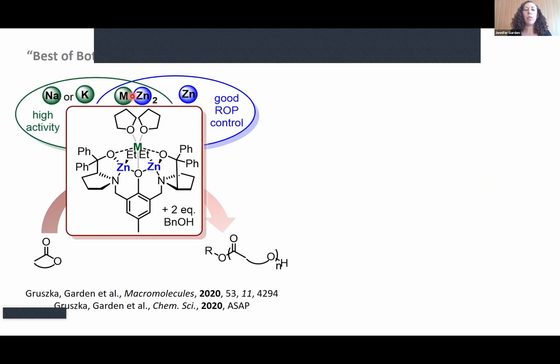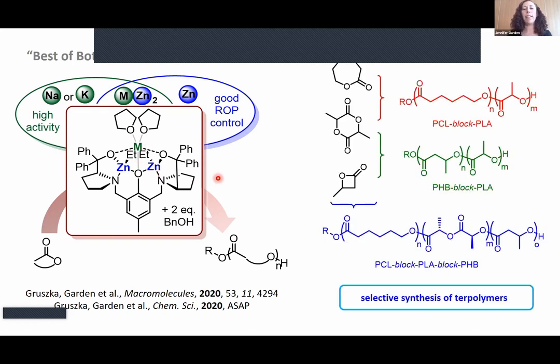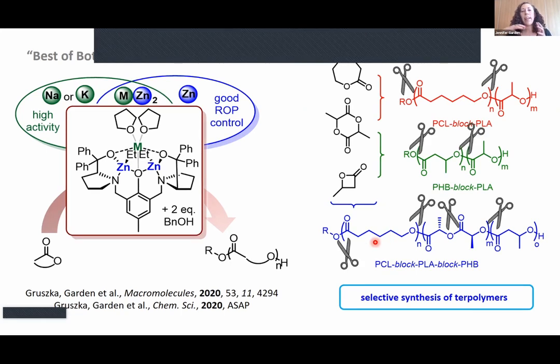And we've also been able to do this with a series of complexes for polylactic acid synthesis, taking complexes that combine an alkali metal, which gives high activity, along with zinc, which gives good control over the polymerization. And using some related catalysts to these, we've also been able to make a range of different materials based on polylactic acid, combining these with other ester monomers. So making block copolymers where we have part of the structure that features polylactic acid and then another part that features polycaprolactone, polybutyrolactone, or a combination of all three. And again, as a key thing, we have these breakpoints from these carbon oxygen units in that polymer backbone.